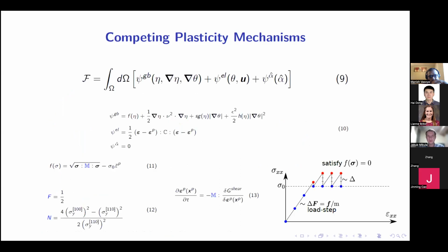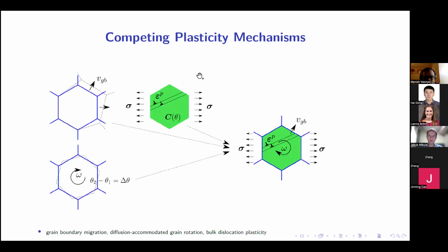And here we again proceed with a phase field model. We built on top of the KWC phase field model, which was used only for grain boundaries, right? This is what we used for generating the grain boundary energy that is misorientation dependent in the martensitic transformation simulations. So now we use this phase field model and extend it by an additional energy contribution: the elastic energy, or strain energy density, as illustrated here, that may also depend on the plastic deformation. So we may also account for a certain plasticity model, such that we are able to model some intragranular deformations.